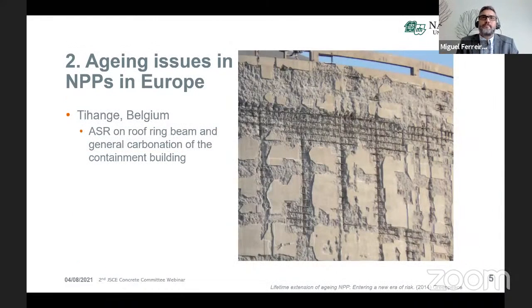And here is one case that I would like to highlight, and here we had ASR. It was found in the roof ring beam. So we have the containment structure, and then on top of the containment structure there's a circular beam around the roof. And there was very poor drainage on top of that roof. So there was accumulation of water. And because of this accumulation of water, the humidity was high. And the aggregate was reactive. So ASR occurred on that ring beam.